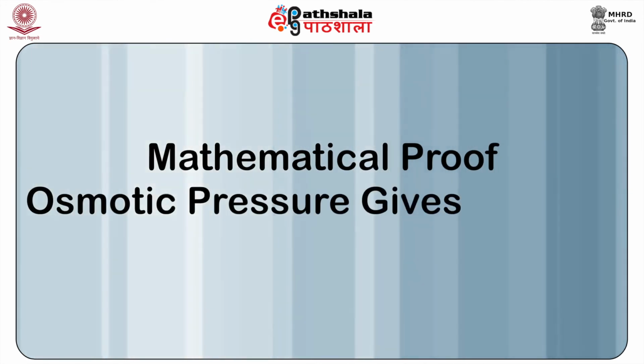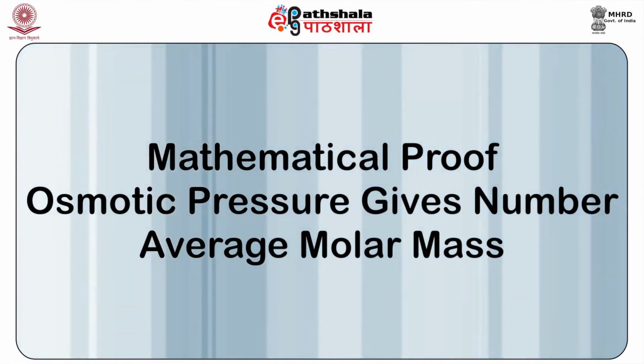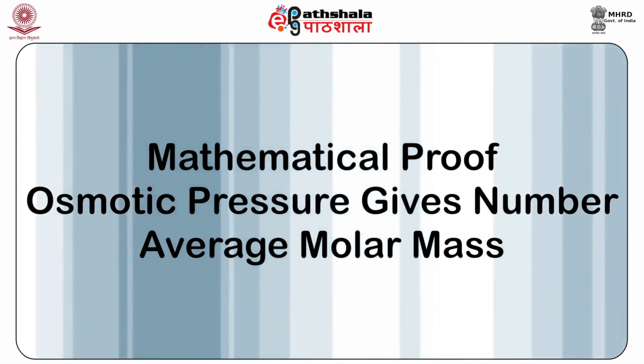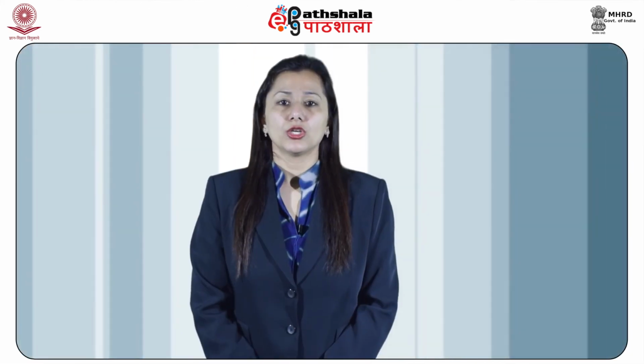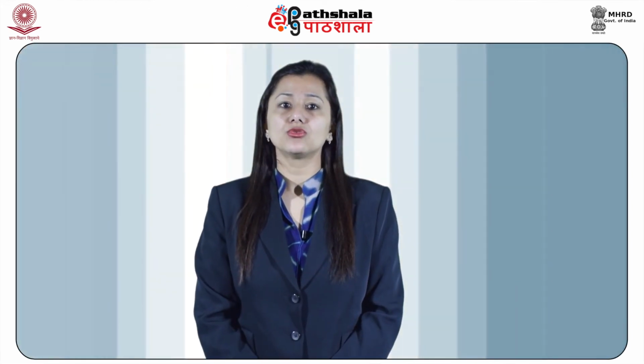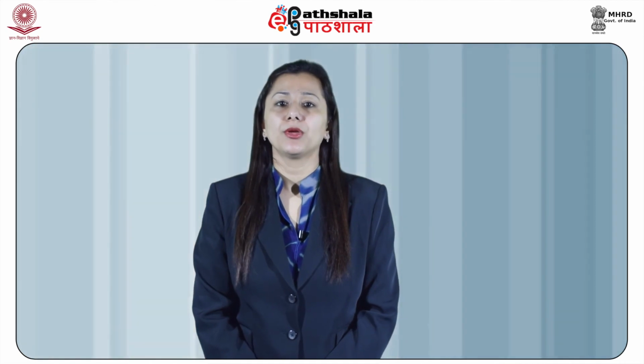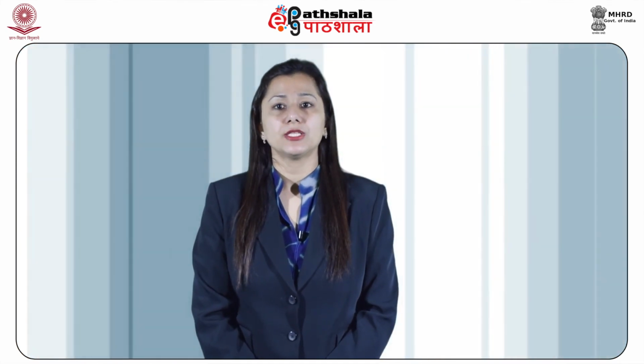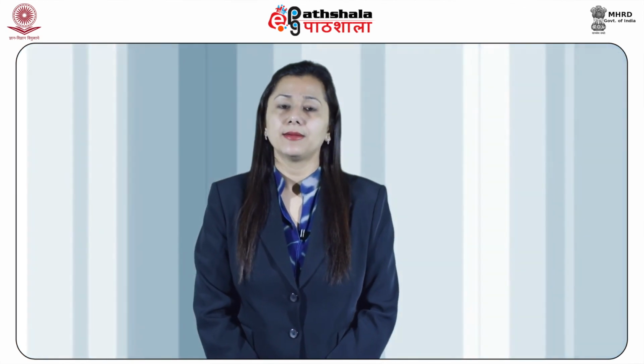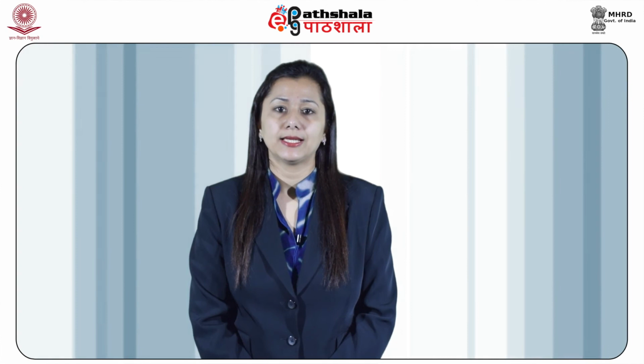Now, we shall see the mathematical proof that osmotic pressure gives the number average molar mass. The osmotic pressure measurements lead to number average molar mass because osmotic pressure is a colligative property which depends on the number of molecules of the polymer and not on their masses. All the molecules, whether heavy or light, make equal contribution.